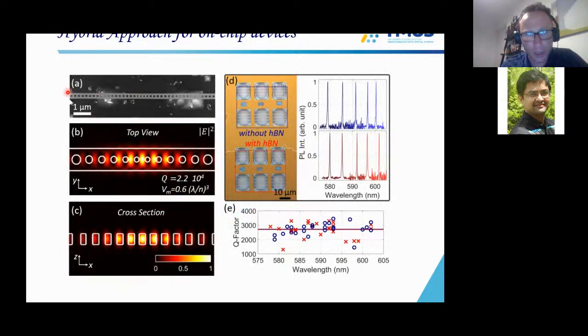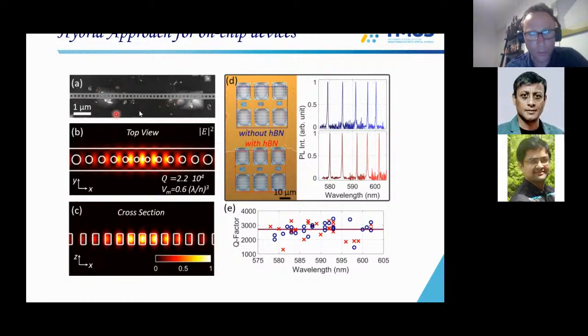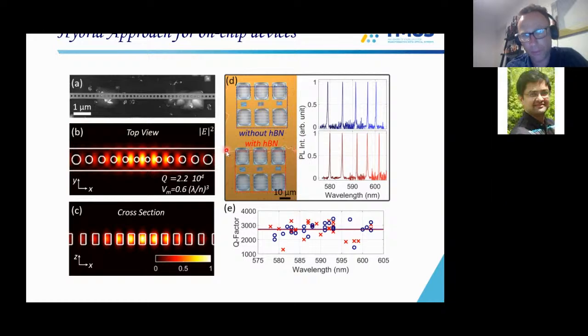So here you can see a silicon nitride photonic crystal nanobeam cavity with an hBN on top. Obviously, you cannot see the hBN, but it's there. In an optical image, you can see it kind of. So this is without the hBN. It's a bit brighter. And this red is with the hBN. So you can see here the contour, the white contour.